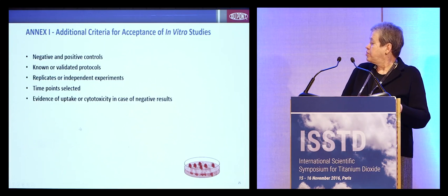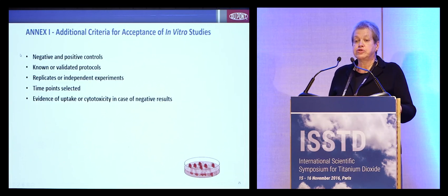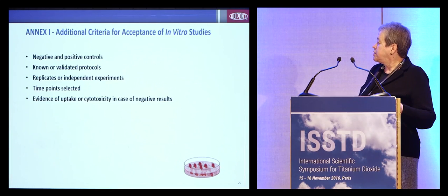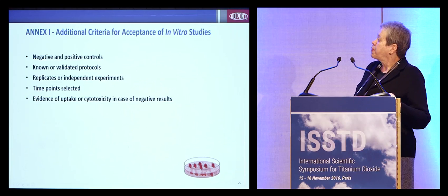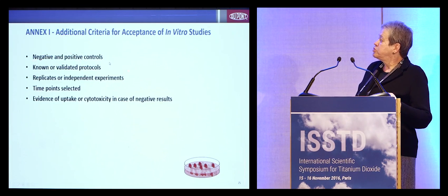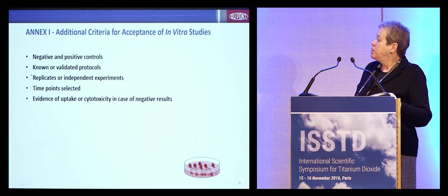Additional criteria for the acceptance of in vitro studies, in vitro is indicated here by this little petri dish down here. Negative and positive control should be included, validated and known protocols should be used, replicates or independent experiments should be conducted, time point selection was important, and there should be evidence of uptake or cytotoxicity in case of negative results.